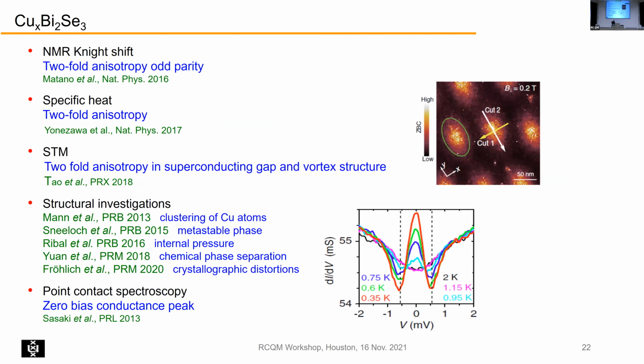For copper bismuth 2 selenium 3, there are a number of interesting experiments that have been done. I mentioned already the NMR, the Knight shift, very interesting. Also specific heat. A very interesting experiment is STM. Here are vortices, and you see these vortices are elongated along a certain direction. This is in a field of 0.2 Tesla. So this also seems to indicate that there is some twofold anisotropy for these vortices.